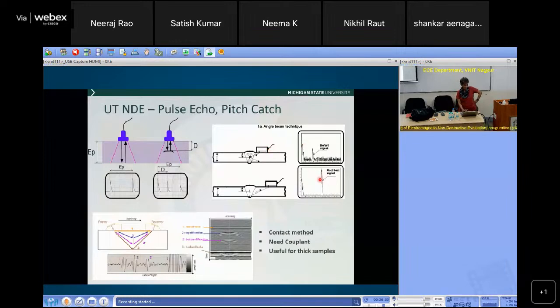signals like this. Now, just looking at one signal individually is very difficult to interpret. If you take an entire measurement, you get a bunch of A scans. So basically the transducer is moving this way, and each A scan is plotted one by one together, and you get an image. And if you have a crack in this fashion, that particular reflection will produce a feature in the image corresponding to the crack. Okay, so ultrasonic NDE is very versatile because waves can travel, say, up to 2 inches of steel and come back. They bring back more information.